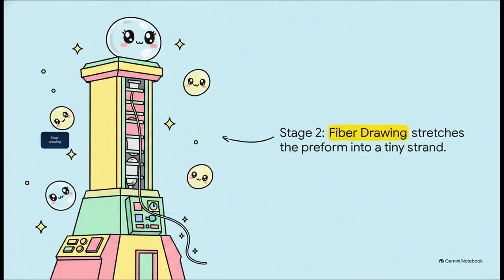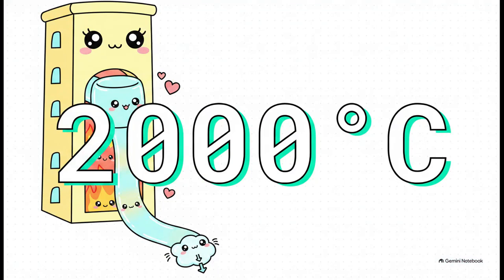That brings us to stage 2, fiber drawing. This is where the magic of scale really happens. That heavy glass preform is loaded into a drawing tower, which is this truly impressive, highly controlled structure that can easily stand over 6 meters tall. Inside this massive tower, the tip of the preform is fed into a furnace and just blasted with extreme heat. We're talking around 2,000 degrees Celsius. That's 3,600 degrees Fahrenheit. At this temperature, the solid glass blueprint softens into a thick, syrupy-like state. Gravity then takes over, pulling a thin strand of molten glass straight down.